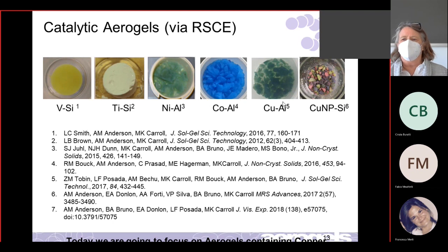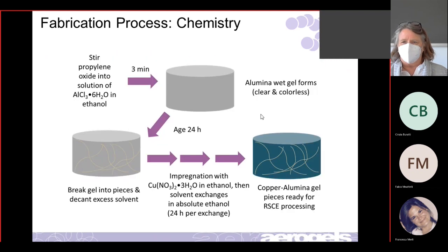So to make it, and Professor Carroll probably showed this slide or something like it, you start with a salt that contains aluminum, aluminum chloride in ethanol, and you stir in propylene oxide, which is a catalyst, and you combine all of that, and in about 3 minutes, you form a wet gel. So it's like a sol gel. And we could take that and rapidly supercritically extract that to get something like that, which we've done.